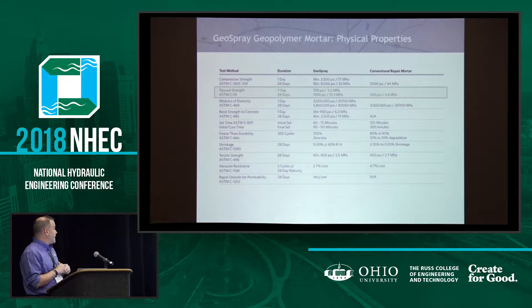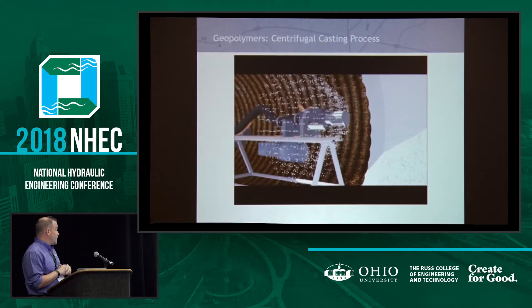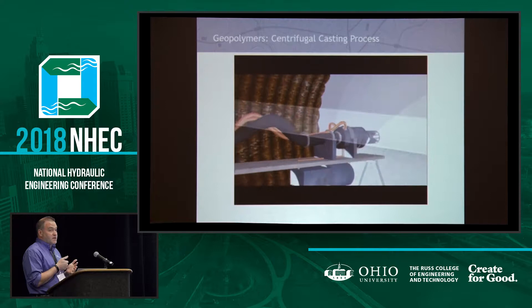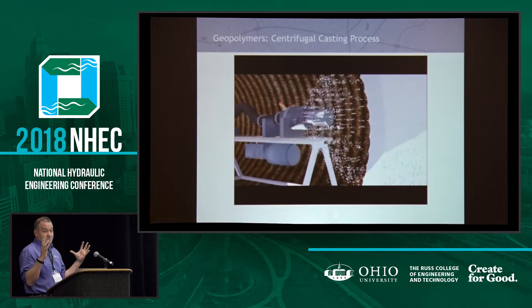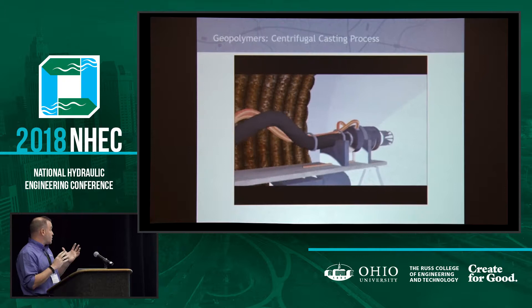If nobody's ever seen this done, there are a whole bunch of different systems that people use, but generally they are pulling some sort of sled with some sort of spin head. Different from normal shotcrete-applied concrete, the spin head can either be air-rotated or mechanical, but you are not putting air into the mortar — you are basically flinging it. High-speed rotation is what's creating the force to throw the material out, so it's not an air-driven process typically, unless someone's applying it by hand. You get really good compaction.